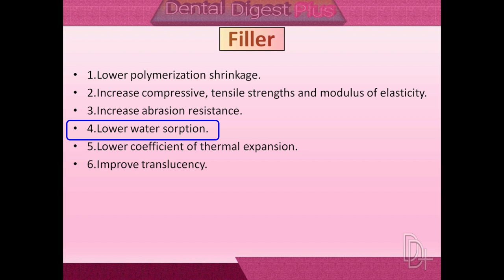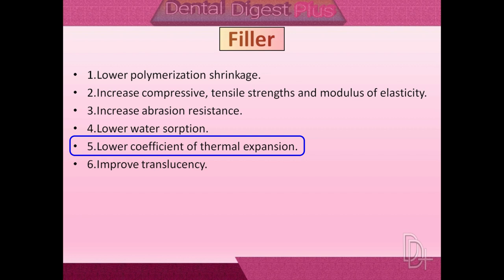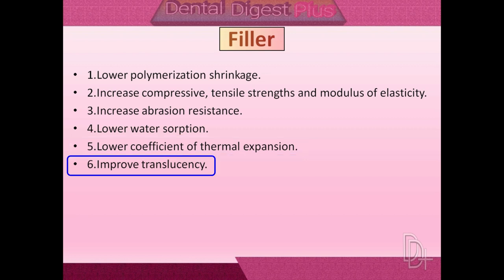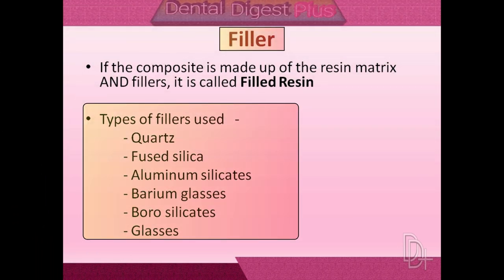There is reduction in water sorption, which reduces the softening and staining of the restoration. There is reduction in thermal expansion and contraction, so less chances of dislodgement of the restoration. Fillers also improve the translucency of the composite material, and in some cases increase radio-opacity and diagnostic sensitivity through incorporation of strontium and barium glass and other heavy compounds that absorb X-rays. Filler particles are most commonly produced by grinding quartz to produce particles ranging in size from 0.1 to 100 micrometers.